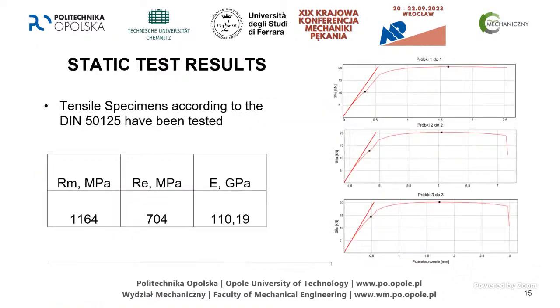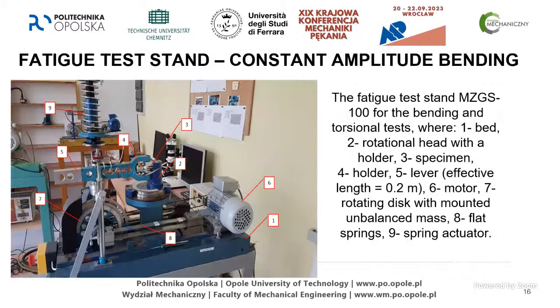As for the static tests, we have obtained the ultimate strength at 1,164 megapascals. The yield strength is 704. The Young modulus 110. As for the fatigue tests, we have used one of our constant amplitude bending test stands, the test stand MZGS 100 for bending and torsional tests. It allows us constant amplitude testing under higher frequencies up to almost 30 hertz.